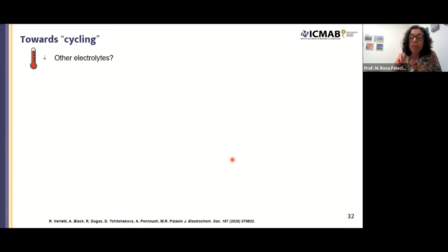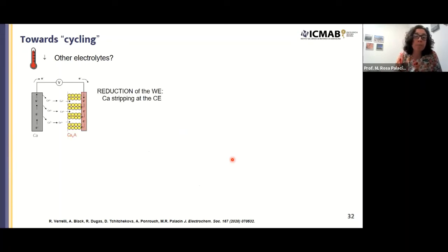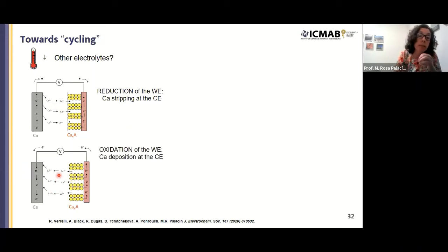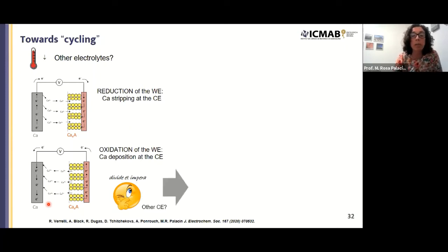But there are not that many available electrolytes, and the issue is that if we use calcium anodes, we need to use an electrolyte enabling calcium plating and stripping, because when you reduce the working electrode and you intercalate calcium, you are stripping calcium from the counter electrode. But if you want to test reversibility, then you need to extract calcium from the positive electrode and plate calcium. So we decided to split those problems and get rid of the calcium counter electrode for the moment and just focus on the titanium.